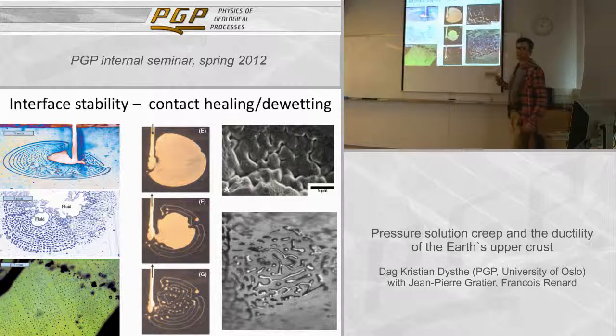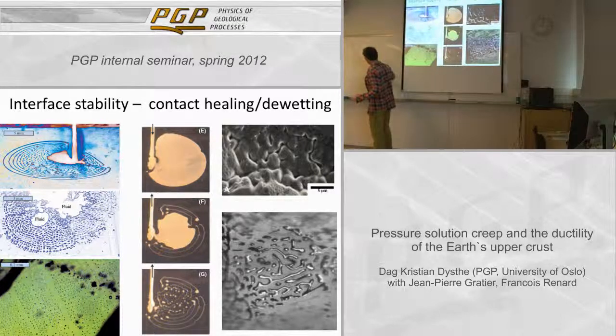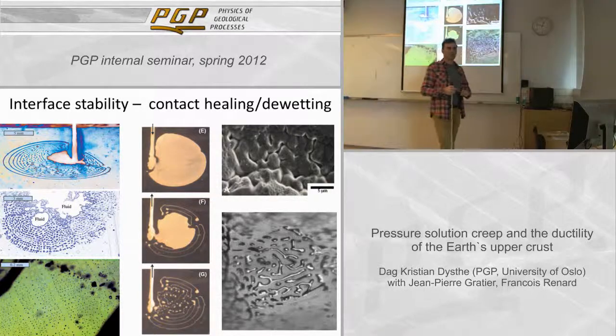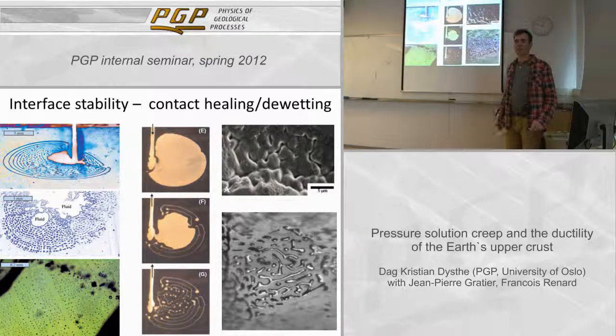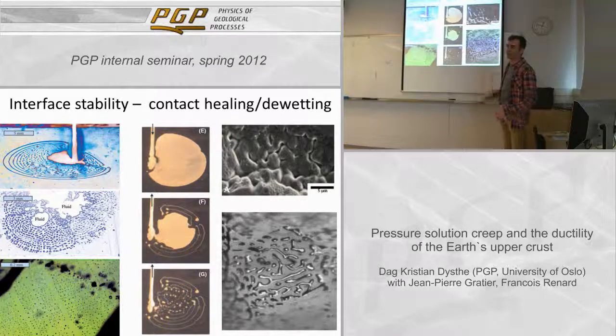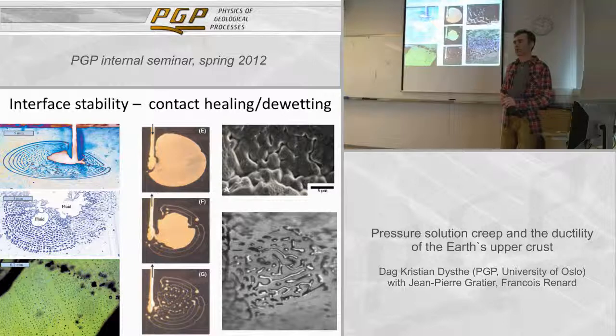And looking at these structures that I showed you that we know are pressure solution contacts, to me some of this looks quite similar to what was a fluid film, a grain boundary with fluid in it, but which has expelled fluid and now has real contact. And when I say a real contact, that means there is no more fluid, that you have atomic bonds directly from one solid to the other, which also means that dissolution and transport becomes much, much more difficult, so at least five orders of magnitude slower. So if this happens to a grain boundary, then it stops the whole process of pressure solution. It just closes it down.